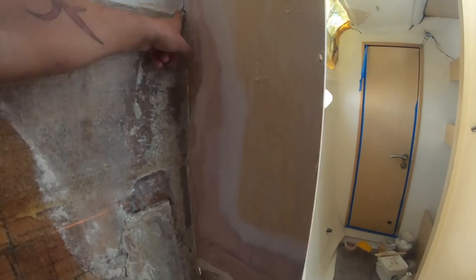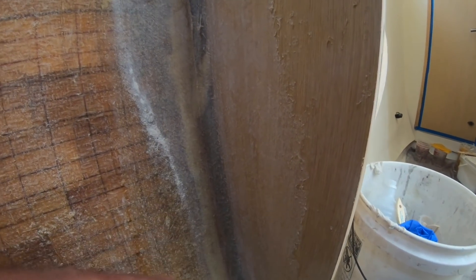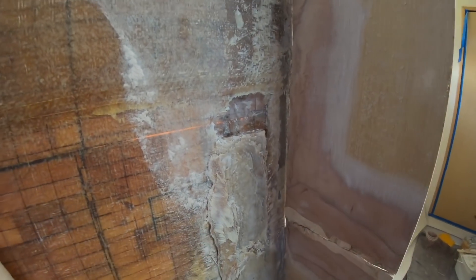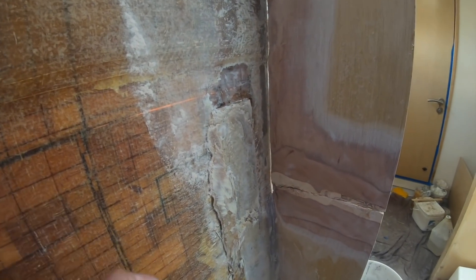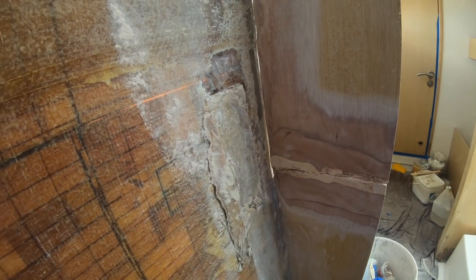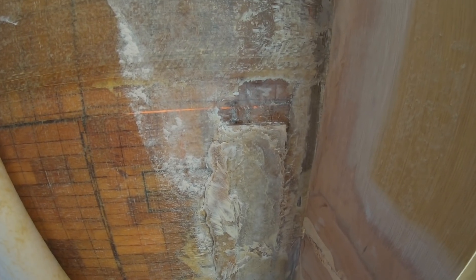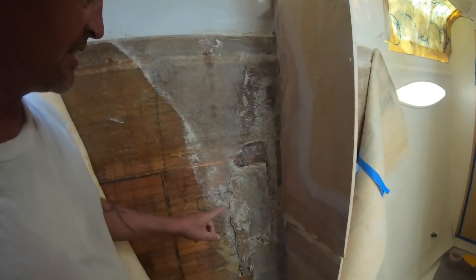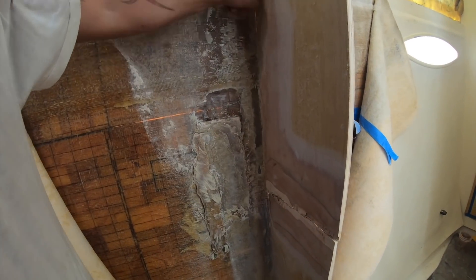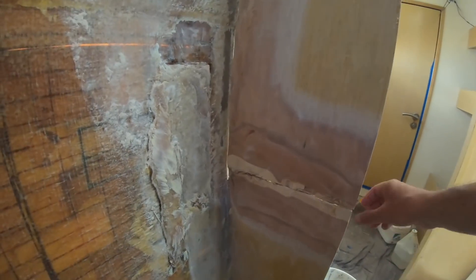To be honest, the way they put it in, it's kind of cheap and easy - they didn't tab it at all on this side. The other side was tabbed in but not very well and extremely screaming thin. So I'm going to use maybe a 1708, something a lot thicker, so I'm going to have to rebuild this area. This area here is actually damage I just found underneath the carpet. This area we have repaired from the outside - someone had already replaced the balsa but when they did, they obviously pushed it all the way back in. So I've done a secondary repair on their patch from the outside. I'm happy from the outside but here on this area I definitely want to cut this back - there's some delamination here. So we're going to grind this area nice and flat, put a nice fillet along here.